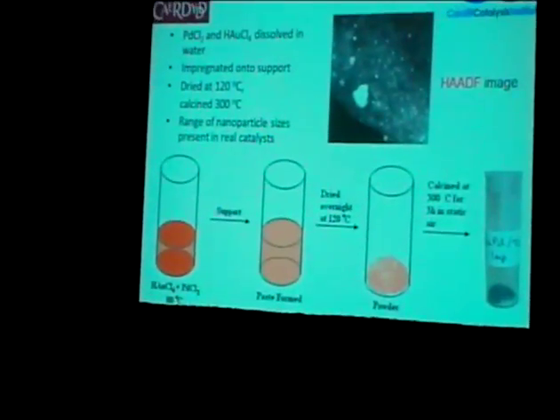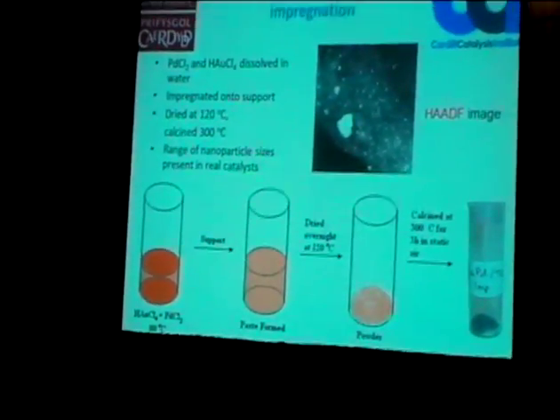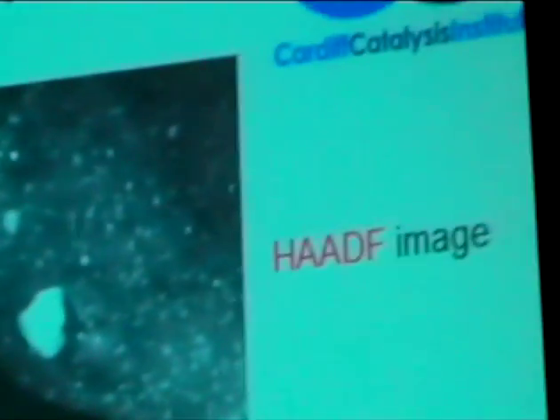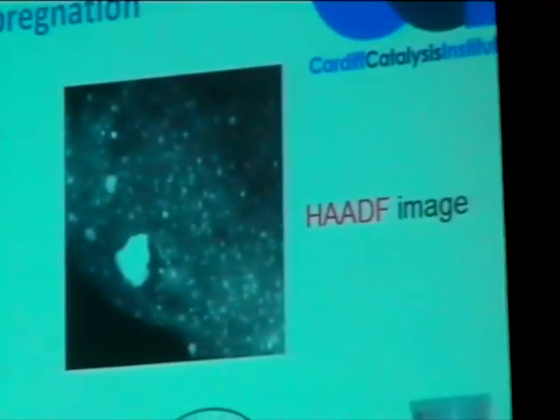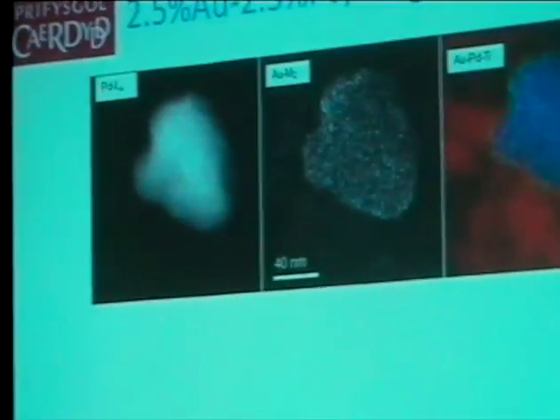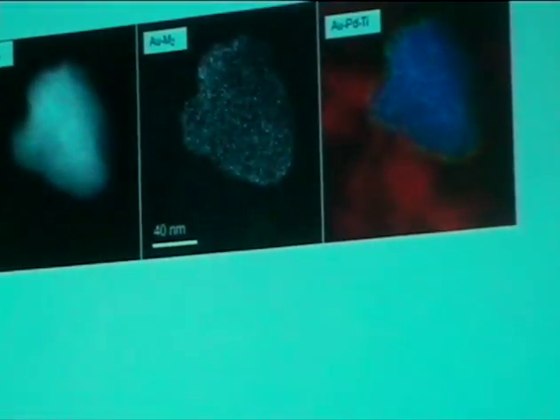Now this preparation method, while being shown to produce gold palladium alloys, has also been shown to produce a wide variety of particle sizes for gold and palladium. You cannot control the particle size very well, as can be seen in the microscopy image of a number of very small gold palladium alloys and also some very large nanoparticles. These catalysts can typically be used for reactions such as hydrogen peroxide synthesis, which I'll come to later.